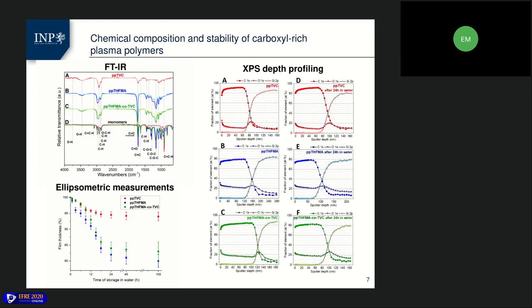In all of the FTIR spectra of freshly deposited films, a stretching signal was recorded at 3,500 per centimeter, and then the C=O stretching was seen at 1730, corresponding to different esters. So this signal was found in THFMA-derived films. Only traces of vinyl groups were seen in the plasma polymerized surfaces, whereas in the monomers, this was much more pronounced. So according to the decrease of this signal, we can clearly see the conversion level in the resulting polymer films. All of the films had the CH signals, and all of them corresponded to different alkane fragments in their structure.